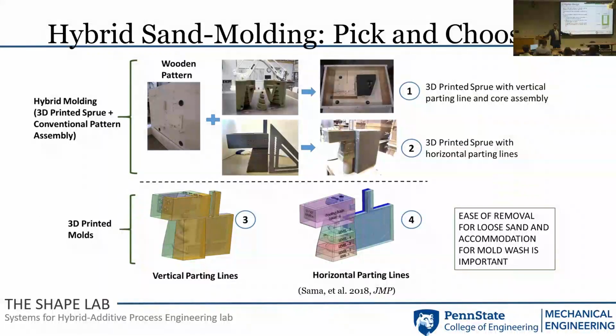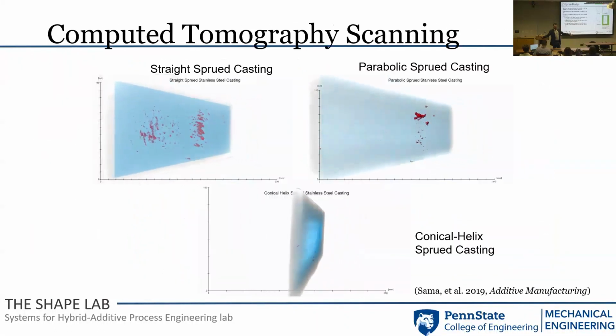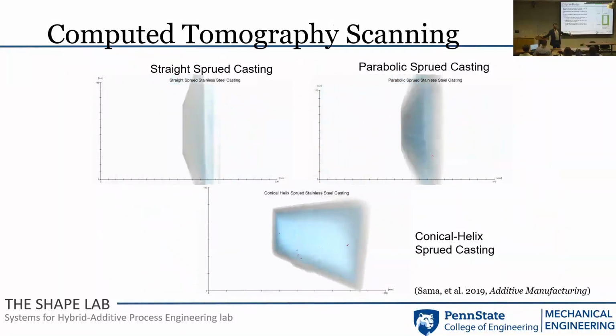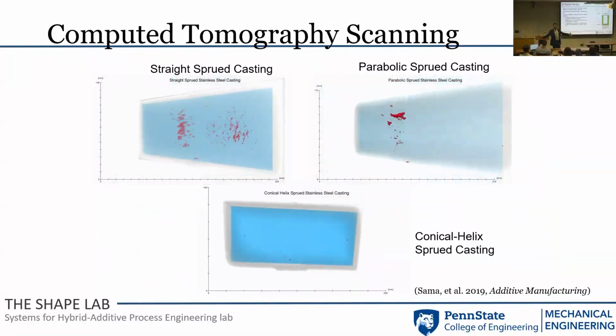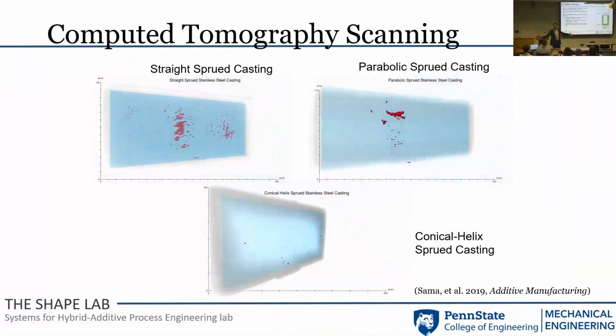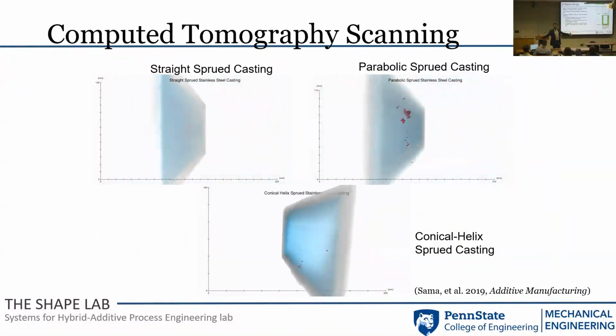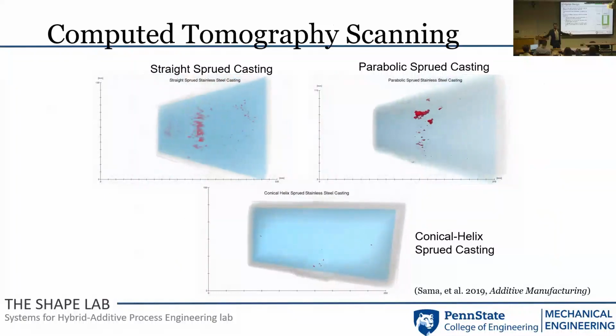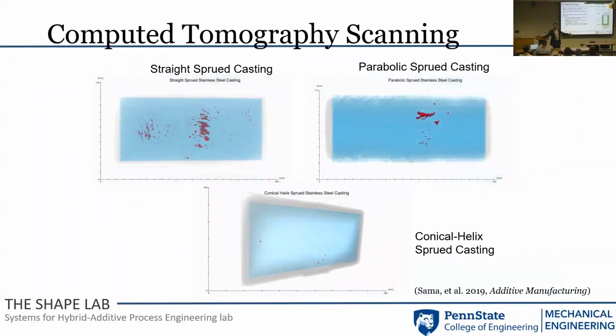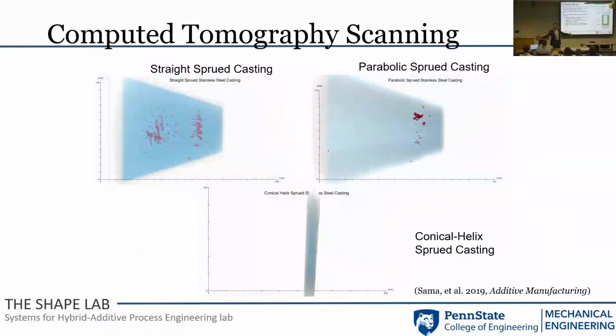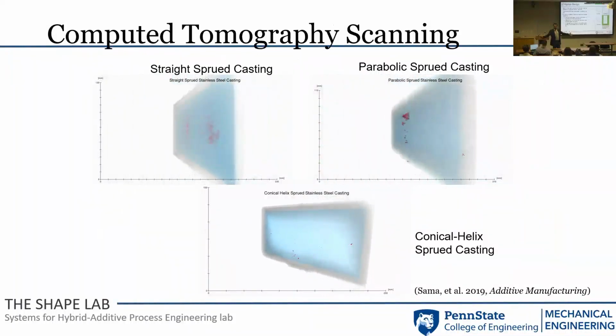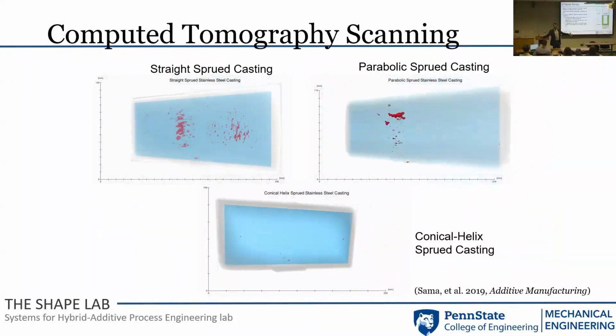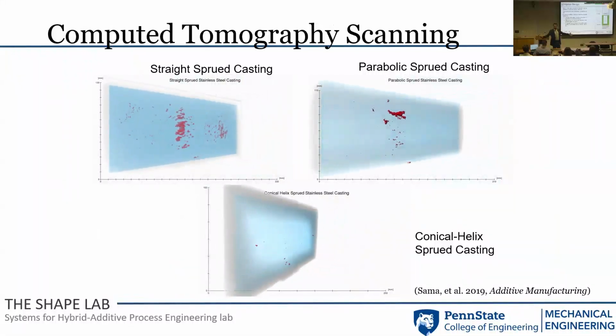Good. You were showing the micro CT data with the defects. What are the common types of defects, casting defects? Oh, everything and anything, in the sense that you will get trapped sand, you will get oxide films, you will get gas pores. You can even get shrink, I mean, you'll definitely get shrinkage associated porosity. So what I say is, you would avoid the first in, first out. Whereas in sand casting, there is no first in, first out. There is first in and it stays in. And it absolutely stays in.